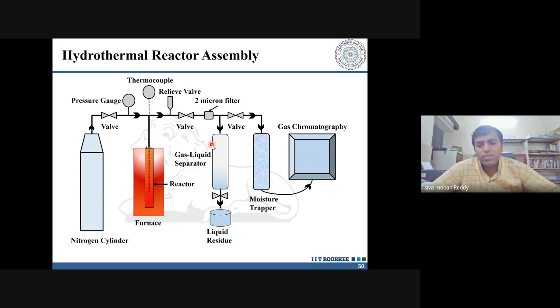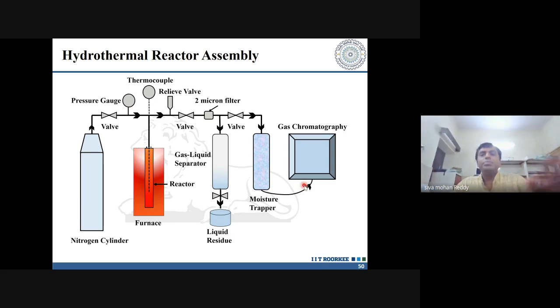It then enters a gas liquid separator, where gases and liquids get separated, and we get the liquid residue at the bottom for further analysis. The gases that are formed are taken out through the top valve, where they pass through a moisture trap just to make sure they are free of moisture. We are using silica gel over here to capture all the moisture present in the gas mixture, and this is directly fed to the gas chromatograph, which works on the principle of TCD to quantify the gases that are generated. Okay, so now I hope you are clear with how the experiments are conducted.